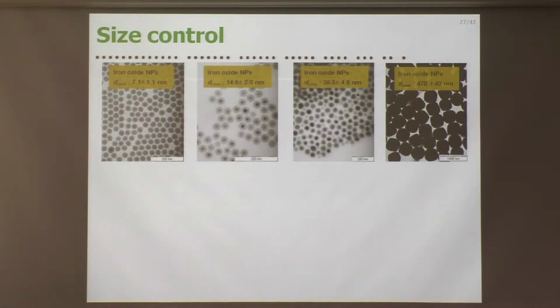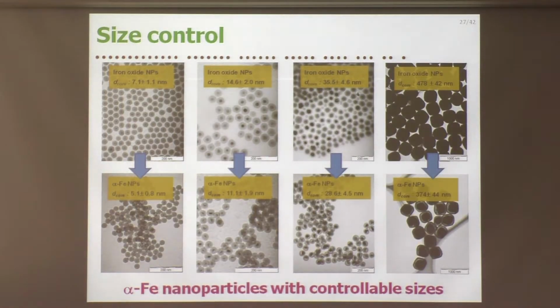As you know, the magnetic properties of nanoparticles strongly depend on particle size, so we tried controlling the particle size as shown here. Here shows the TEM image of the iron oxide nanoparticles with different sizes. Of course, we can reduce this to form alpha iron nanoparticles with different sizes.